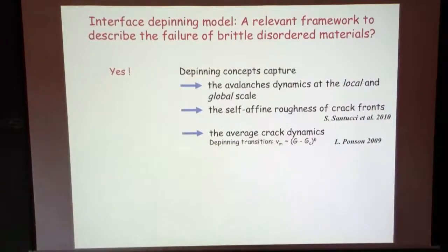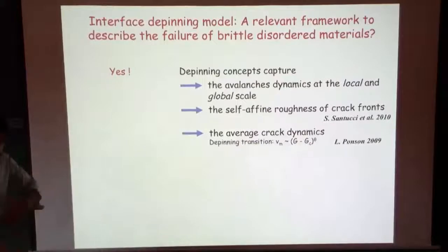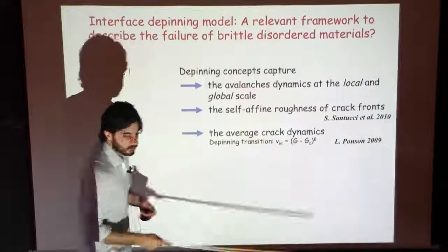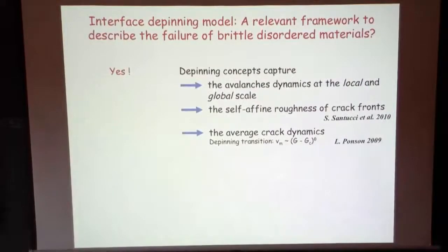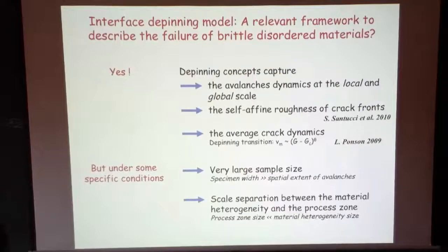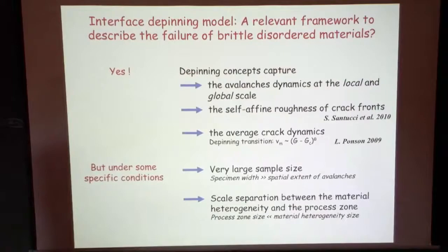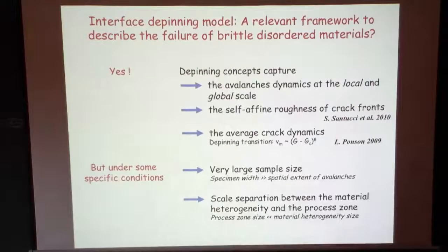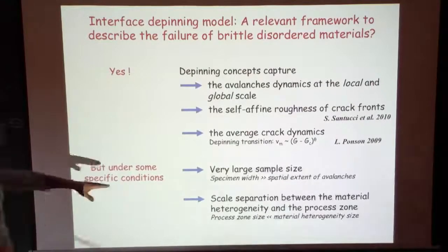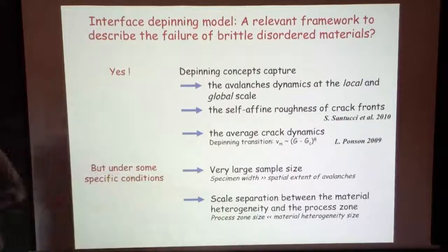These two points I didn't talk about. You can actually measure the depinning transition. If you measure your average velocity versus driving, you can have this so-called depinning transition where the velocity goes from 0 to a power law, evolving as a power law of the distance to the critical threshold. So you can really explain a certain number of things, but you need to look at a fracture problem under very specific conditions that are not the general case. I've quoted two specific restrictions that make that model apply.